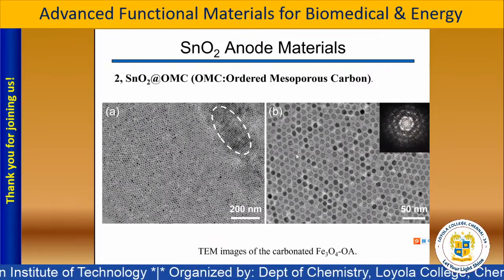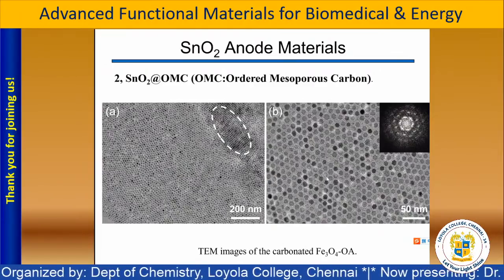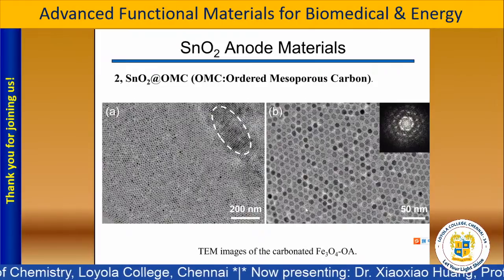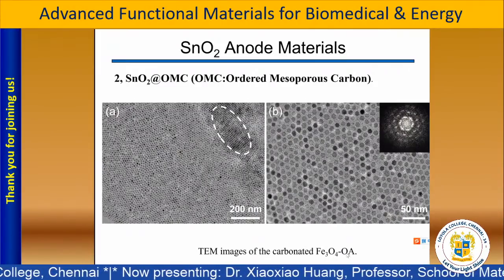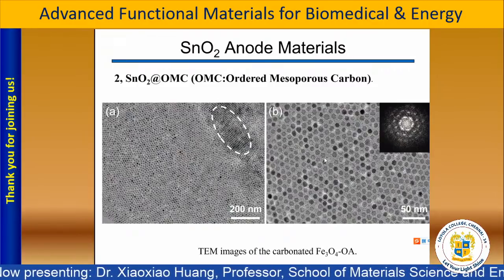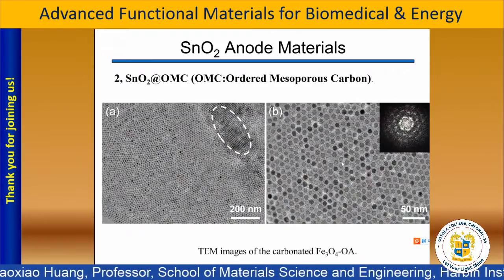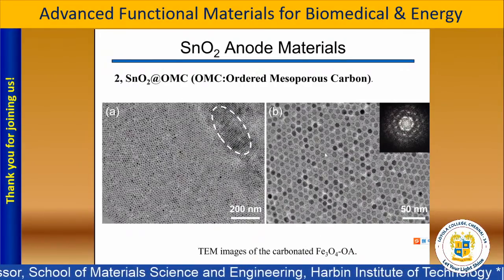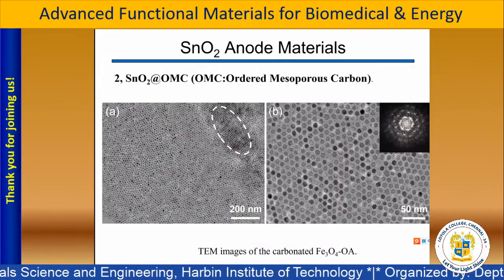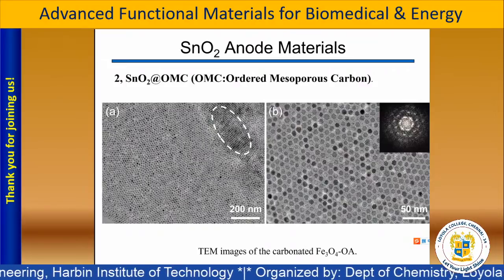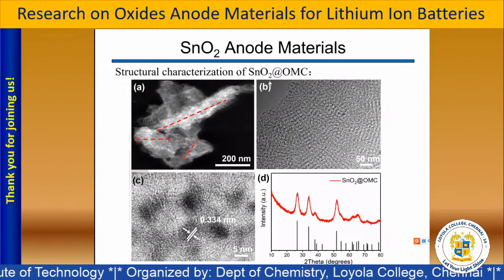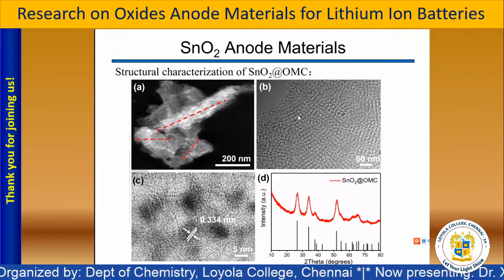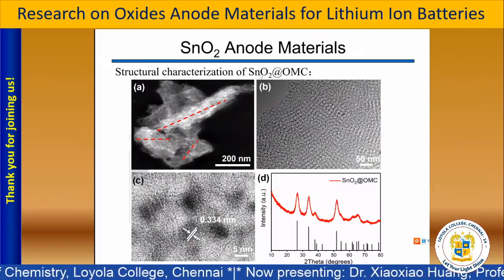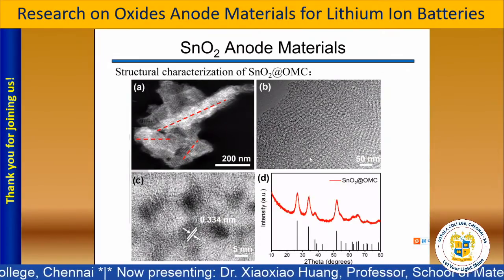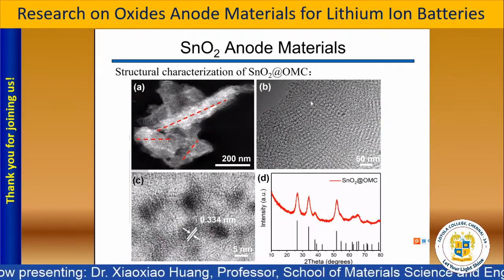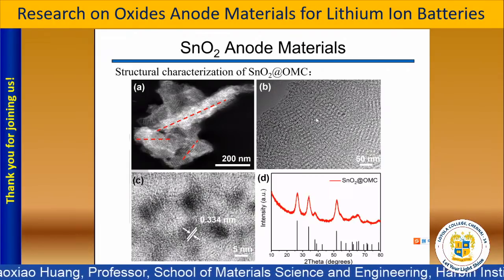Let me show the microstructure of the materials preparation process. These two pictures are about the ferroferric oxide with OA. And we can see that after the solvent evaporates, the ferroferric oxide particles are orderly arranged by self-assembly. And after the ferroferric oxide is removed, we got the tin oxide at OMC material. From this picture, we can see that the hollow carbon copies the ferroferric OMC structure.